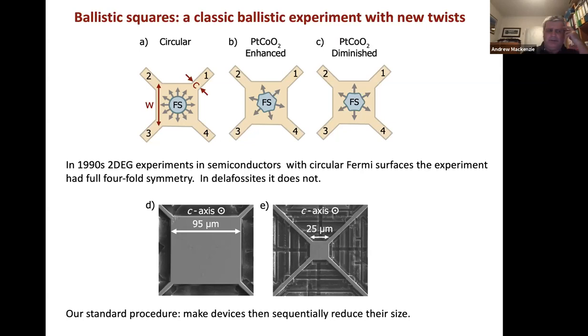And we did it in the usual way. If you work with a focused ion beam, we made the squares. The biggest one, Philippa and Elena made, had a 95 micron side. And then we would sequentially cut the squares down, so that here's this same square cut down to 25 microns. And you can basically more or less, if you're careful, retain the width of the current and voltage leads as you do that.